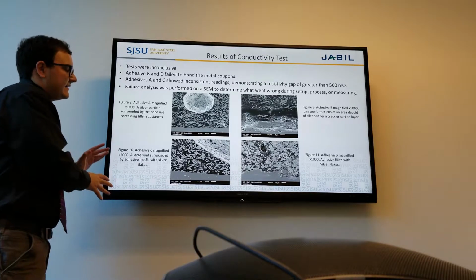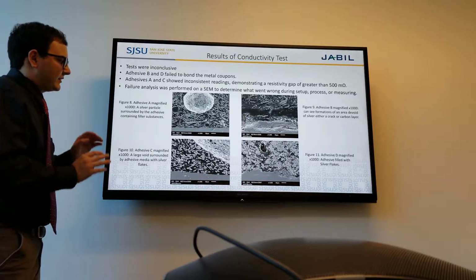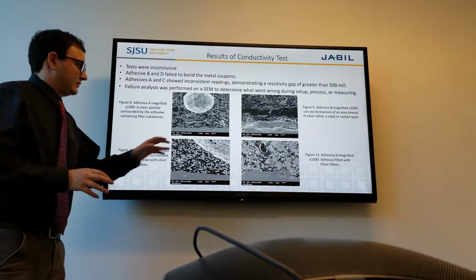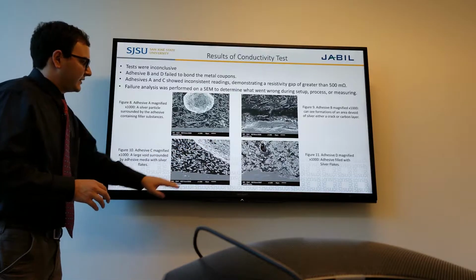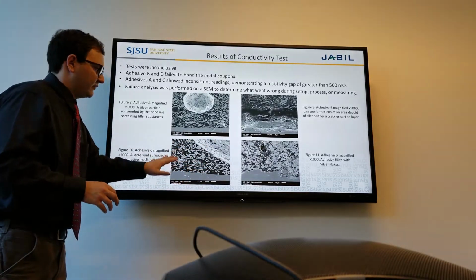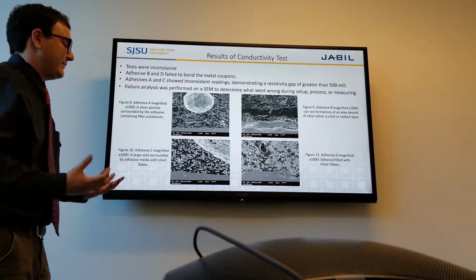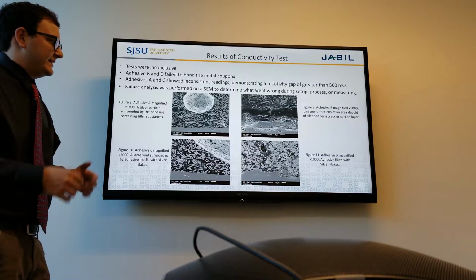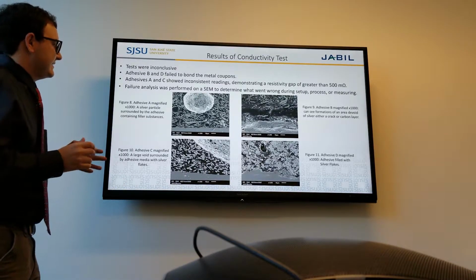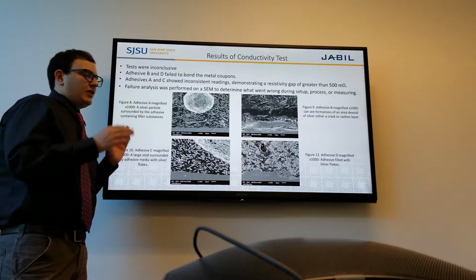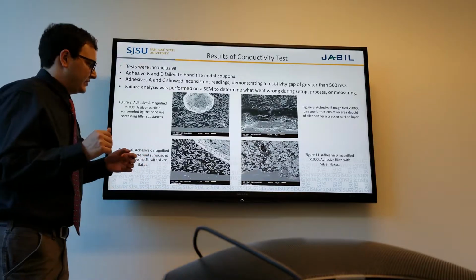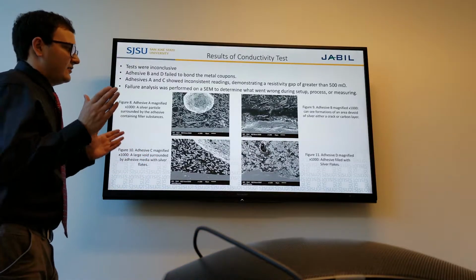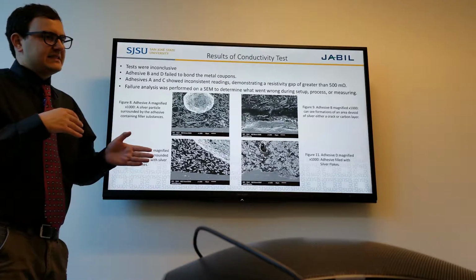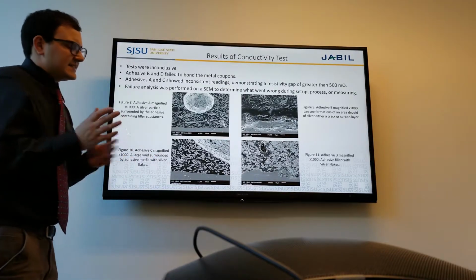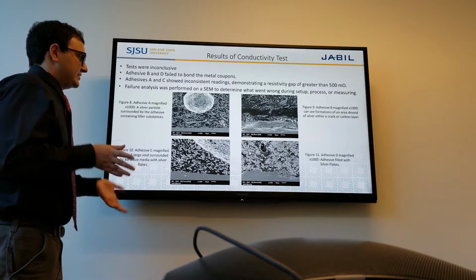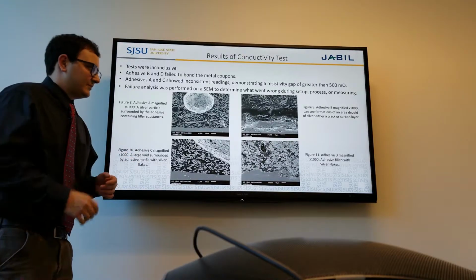And what that meant was that it didn't have the strength to support the weight of the stainless steel coupons. Adhesive C had the strength to support the coupons, but there were void areas. There were large air bubbles in certain parts. There are void areas devoid of the silver, which actually makes the conductivity happen. And there's no consistency between it, which meant that there was a large range. There was no telling this coupon is going to have more void versus this coupon is going to have less void. And that gave us a large resistivity range, which made the results unusable.